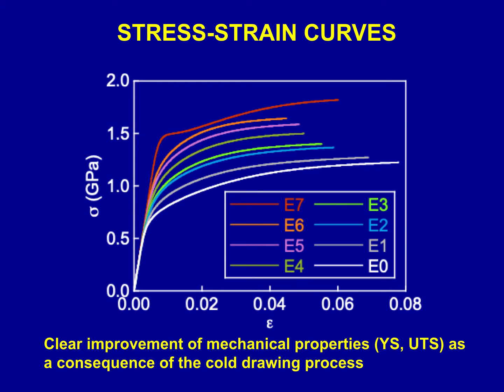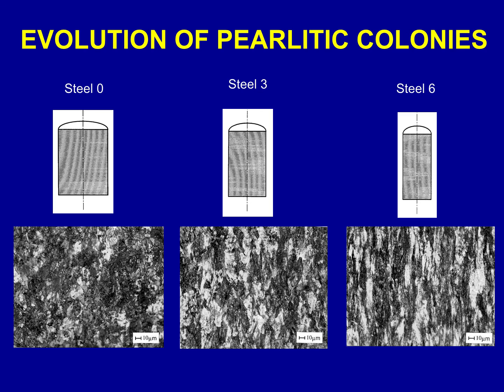Here we can see from steel 0, hot rolled material that is not cold drawn at all, then 1, 2, 3, 4, 5, 6, 7 steps of cold drawing, with increase of both yield strength and UTS. The evolution of pearlitic colonies, here for 3 levels, steel 0, 3, and 6, undergoing 0, 3, and 6 steps of cold drawing. We can see a progressive orientation and slenderizing of pearlitic colonies. They become enlarged, slenderized, and oriented in the vertical side of the slide, y-axis or cold drawing direction.